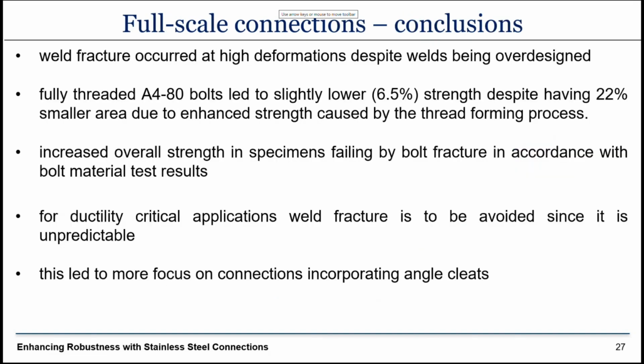And the conclusions we reached were, first of all, if you have a ductility critical application, avoid welding. We did try to eliminate welding as a possible failure mode. We didn't want to go into the microstructural effects of welding in the vicinity of the material, and that's why we oversized the welds. Nonetheless, at high deformations, we did get, in some cases, weld fracture. Fully threaded A4-80 bolts led to slightly lower strength despite having 22% smaller area, due to enhanced strength caused by the thread forming process. We saw that an increased overall strength in specimens failing by bolt fracture was obtained.